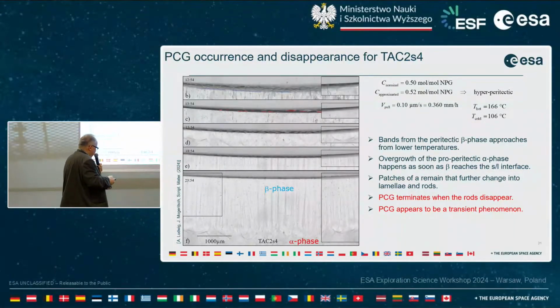Here's a larger overview, and what we found out is that we have the original initial alpha phase, which is an important thing to know. That is really the alpha phase at the beginning, and not another phase. And then the beta phase forms, coming from this NPG-enriched channel, and tries to overgrow the alpha phase.